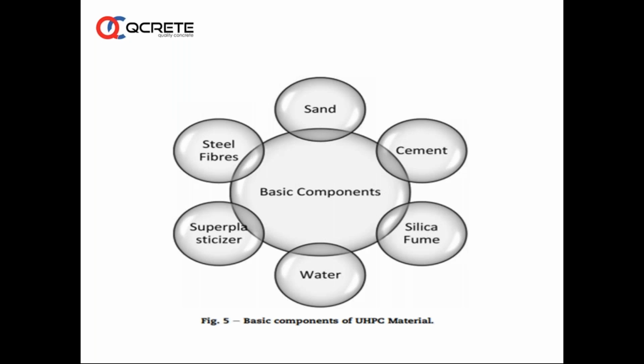So this is a picturization of the components of UHPC material. You have sand, cement, silica fume, water, superplasticizer. These are the basic components. Added to that, you have steel fibers, which are very important in increasing the ductility, toughness, and tensile strength.